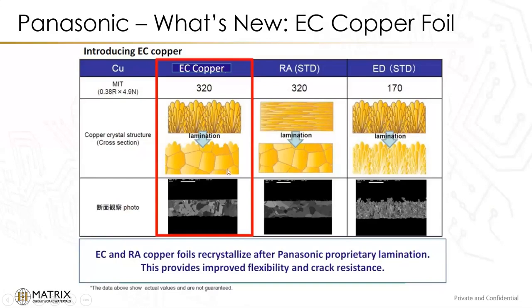But what it does, though, is it gives actual improved flexibility and crack resistance. So it goes through this recrystallization process through the proprietary lamination cycle that Panasonic uses with that. And then you can see in the SEM photos of the cross-section how those structures are actually changed. So this gives it a very good product that can be used, high reliability, especially with that, and crack resistant.